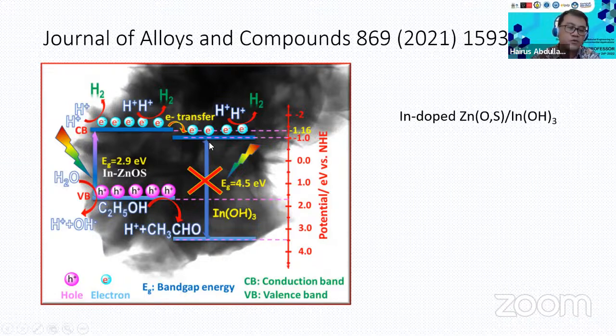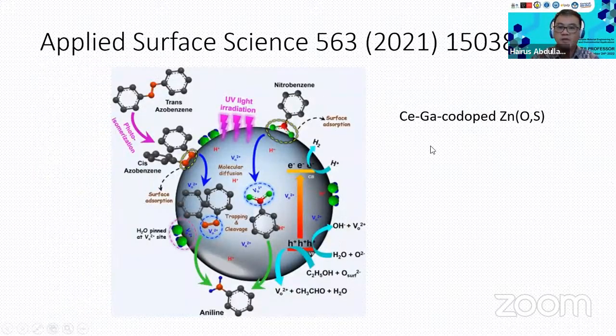This work is used for hydrogen evolution reaction under visible light illumination. And then the next one, I also did not show the characterization, but we have a cerium and gallium doped Zn(O,S), which can be used for different kinds of chemical conversion. This basically shows the nitrobenzene and azobenzene adsorbed on the surface of the catalyst because of the oxygen vacancy.